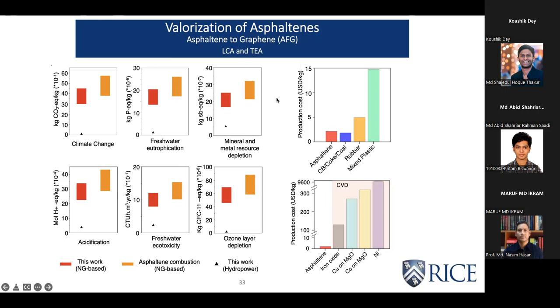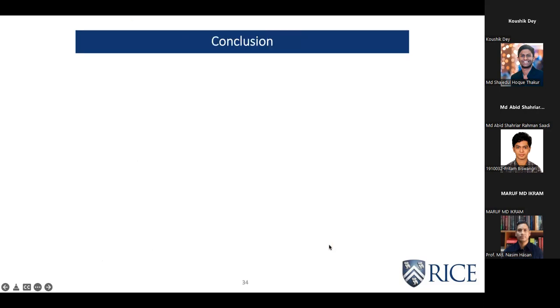The TEA also helped us determine the production cost of asphaltene-derived flash graphene compared to other flash heating precursors, and we saw a feasible cost for asphaltenes, and it's significantly better when you compare it with CVD grown graphene. These are not comparable because the structures and the properties are very different. But if you look at the production cost compared to the different types of CVD grown graphene, it's significantly cheaper. So with that, I would like to end and summarize my talk.